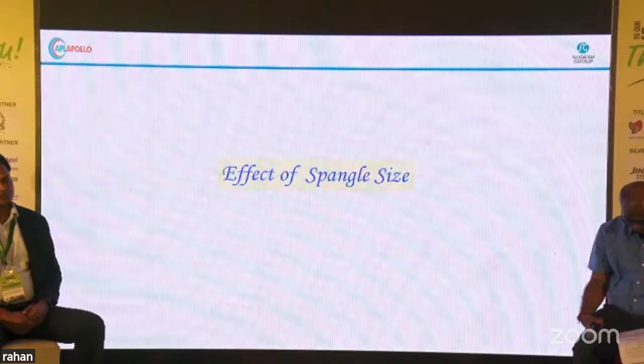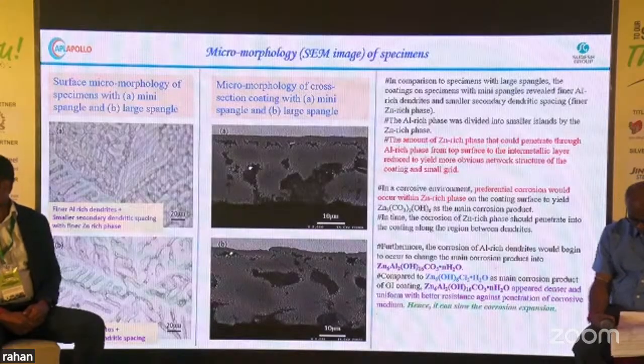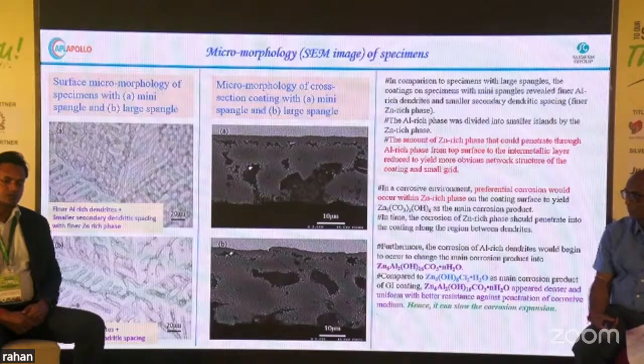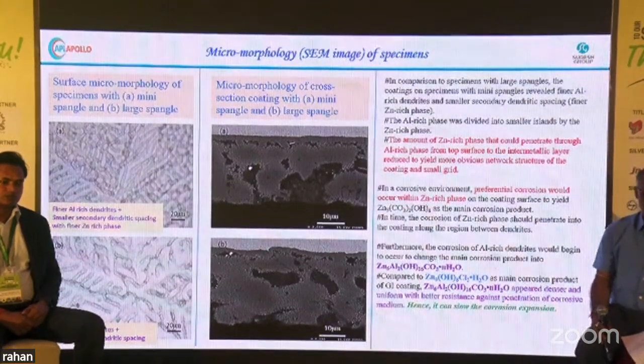Now the first thing is the effect of spangle size. In our study, it ranges from 0.5 mm to 4 mm. 4 mm is the large spangle in case of Alu-Zinc, and 1 mm is called mini spangles. So what is the impact of spangle size on the corrosion resistance? The top left side is mini spangle, and the bottom left side is the big spangles. In the middle, this is the SEM, the cross section of the coating. On the top is mini spangle, and the bottom is large spangle.